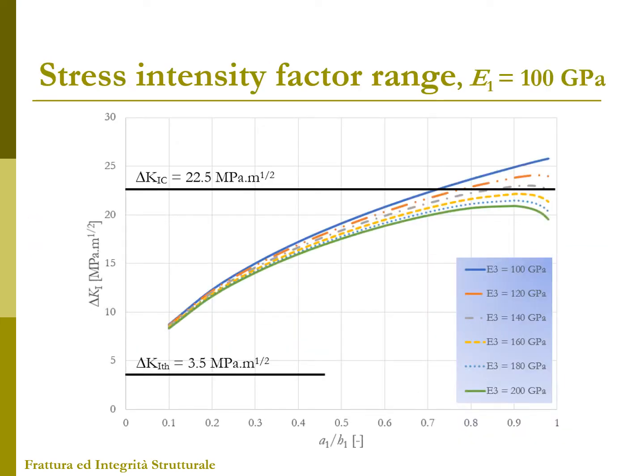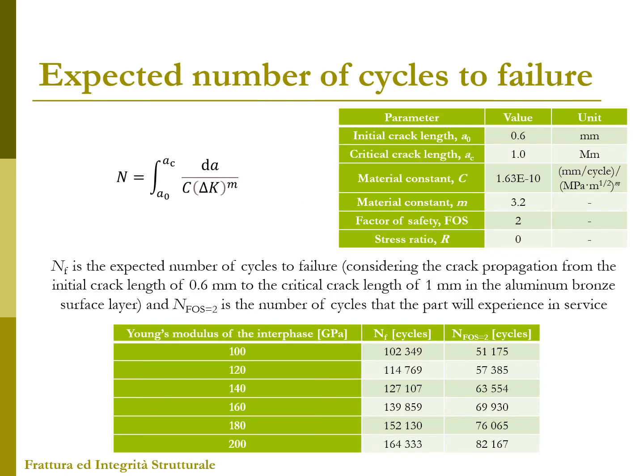And here, the dependencies of the stress intensity factor range on the relative crack length for various values of the Young's modulus of the interface can be seen, together with the threshold stress intensity factor range and critical value of the stress intensity factor range. Moreover, the expected number of cycles to failure was estimated from the Paris-Erdogan law. Again, you can see the parameters used within the calculations and finally the results in dependence on the Young's modulus of the interface layer.